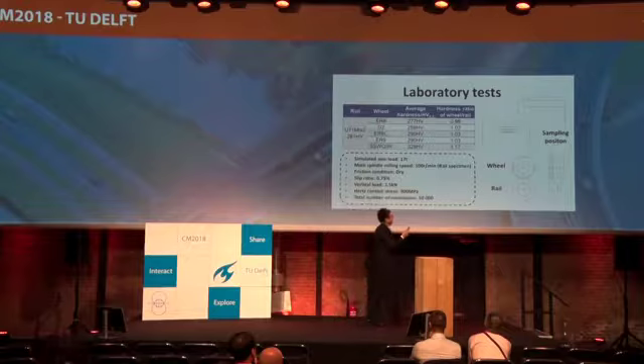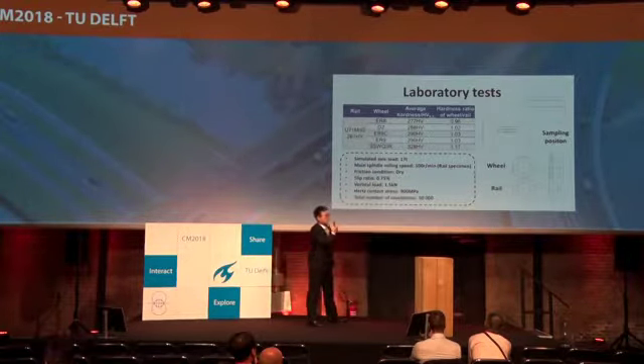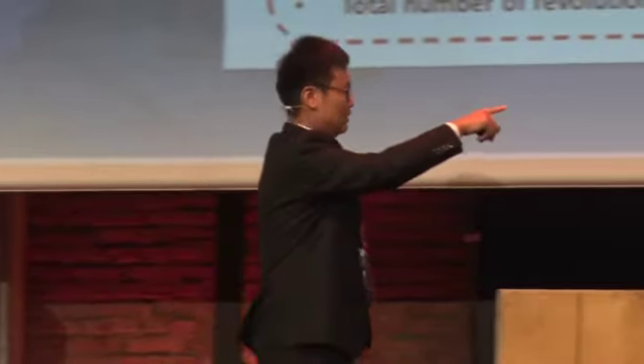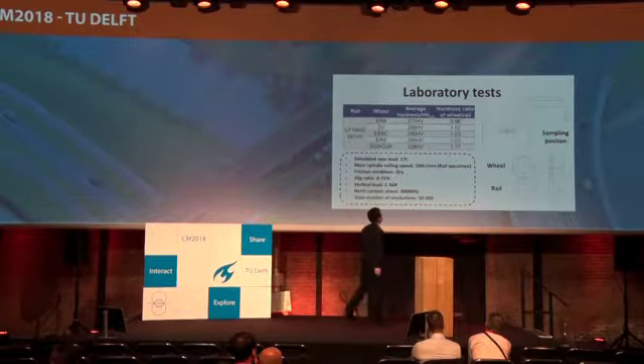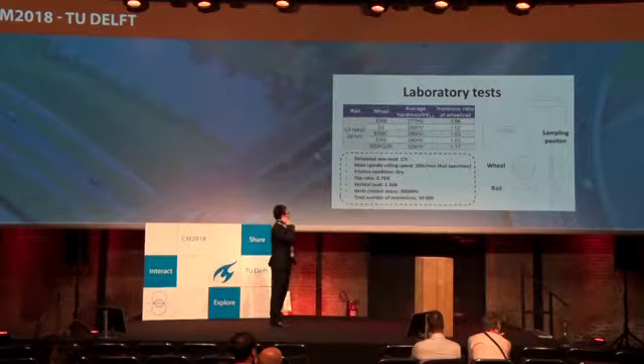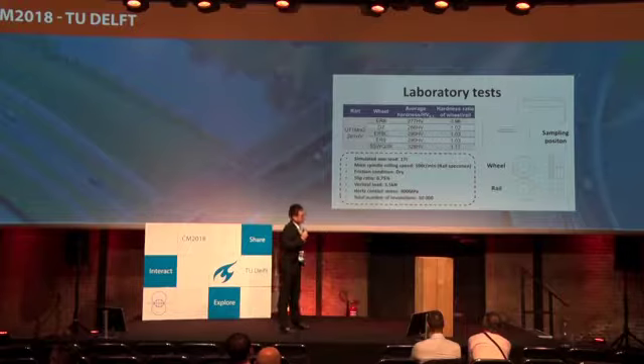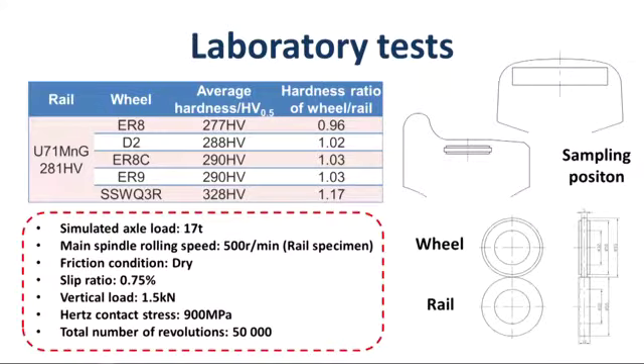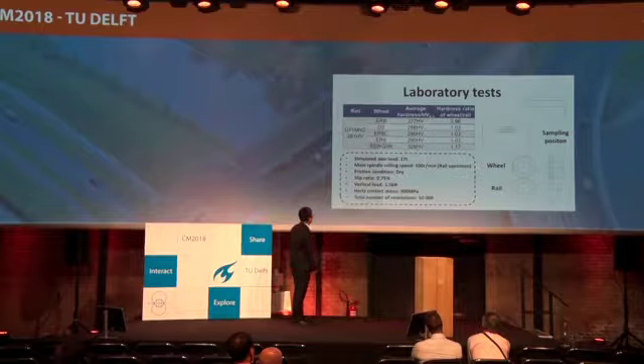And the testing apparatus was, sorry, I didn't put a picture here, but the twin disc testing apparatus was shown in this figure. And the test parameters are shown here. We simulate the axle load set as 17 tons, which is the axle load of the CRH3 EMU type in China. And the rolling speed is 500 rounds per minute. The friction condition is very simple, it's dry. Because we have the same condition, we can compare different materials. And the slip ratio is 0.75%. Vertical load, 1.5 kilonewtons. And in that, we got the Hertz contact stress of 900 megapascals.